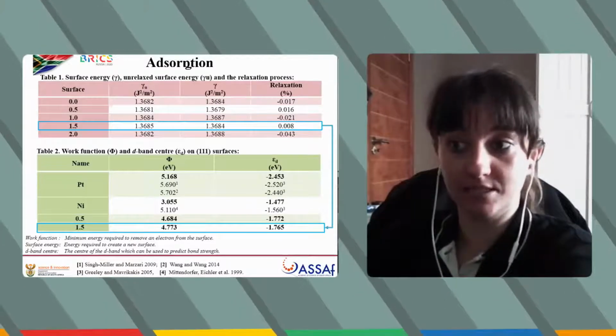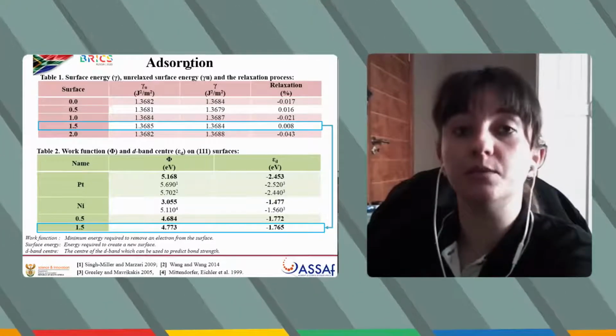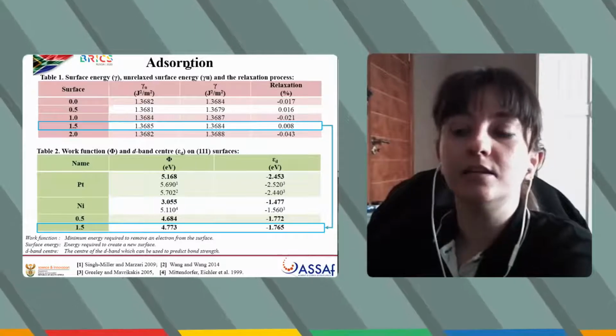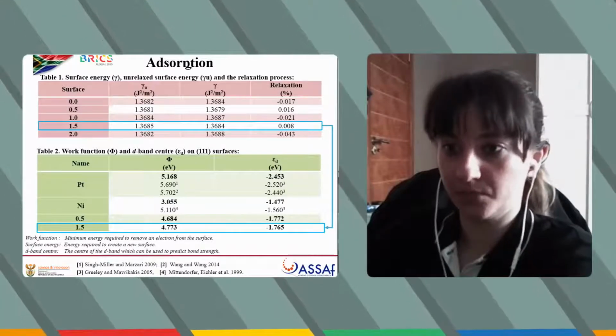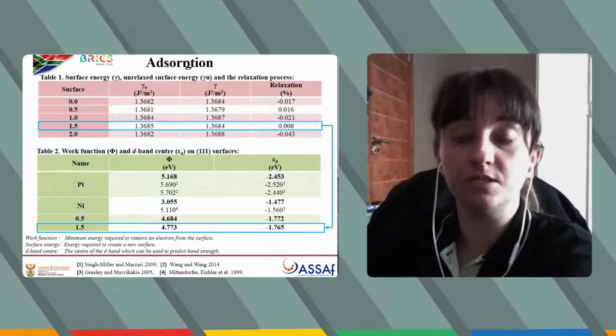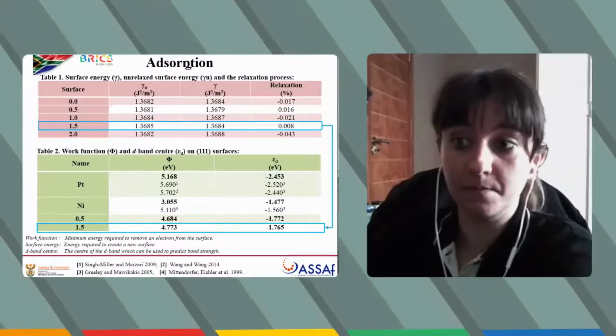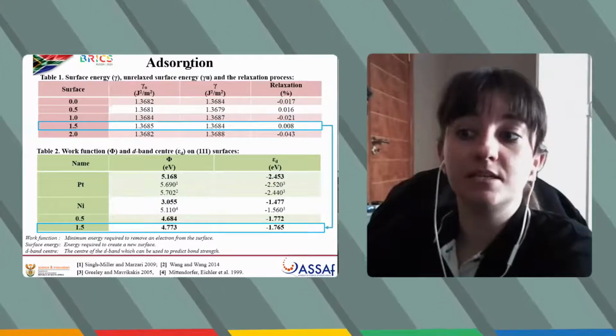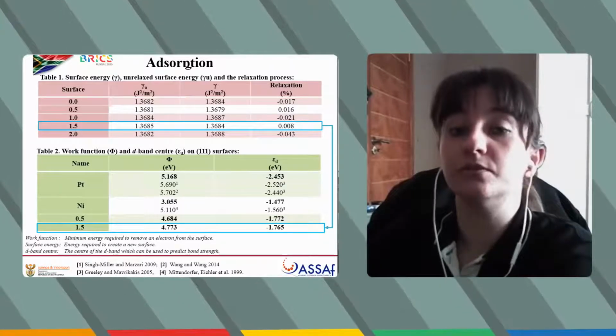Looking at the D-band center, stronger bonding will occur between the adsorbate and the nickel surface, but weaker on platinum. The D-band center of the bimetallic surface is between that of platinum and nickel, which means that the bimetallic surface is more suitable for surface reactions.